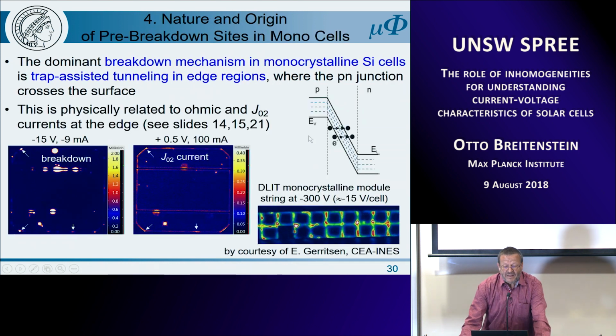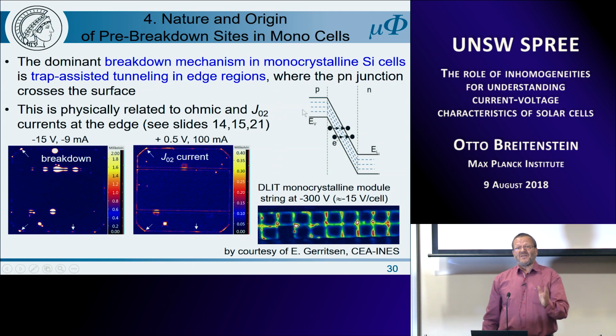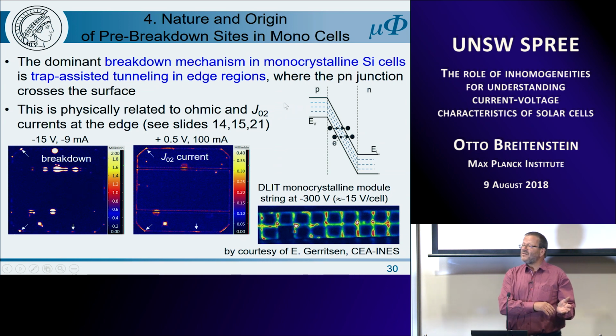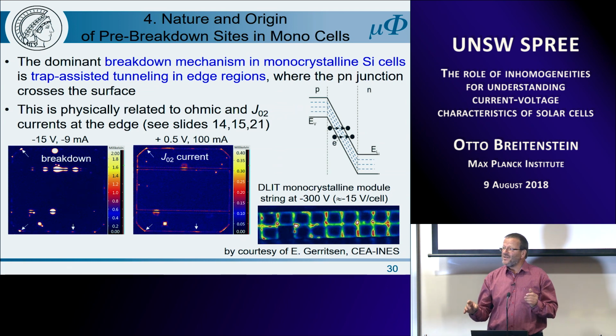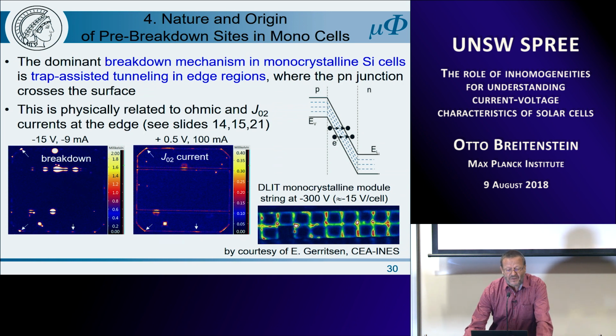And finally, if we have a monocrystalline cell, then from these breakdown mechanisms, actually only the aluminium-induced breakdown is expected to occur. But we also found in perfectly made solar cells some breakdown. And it is in particular at the edges. So this is, by the way, the same monocrystalline cell I have shown some results already before.